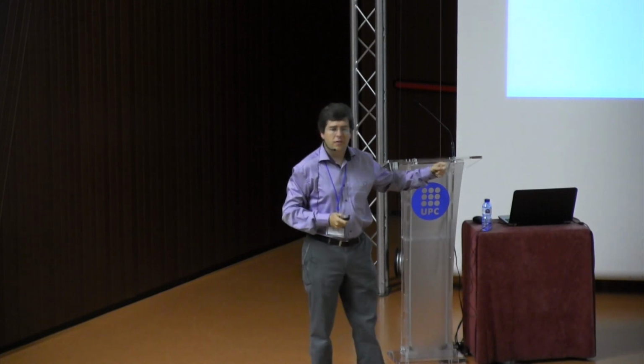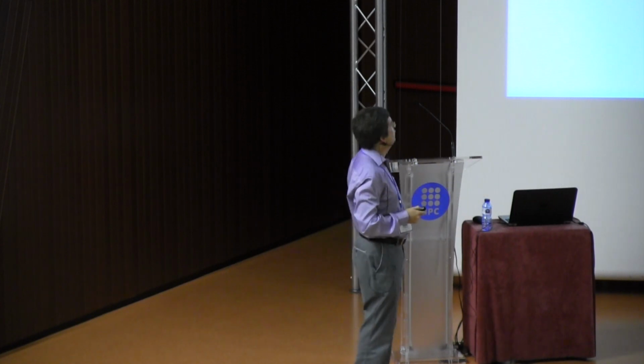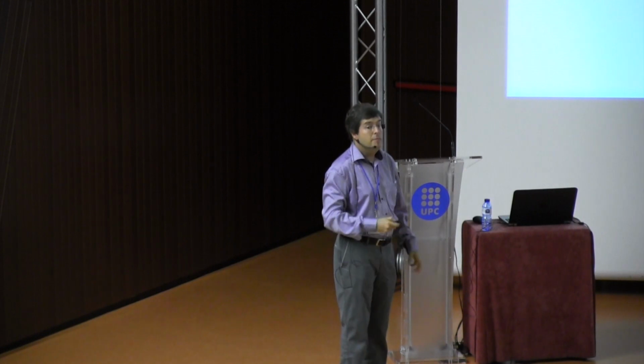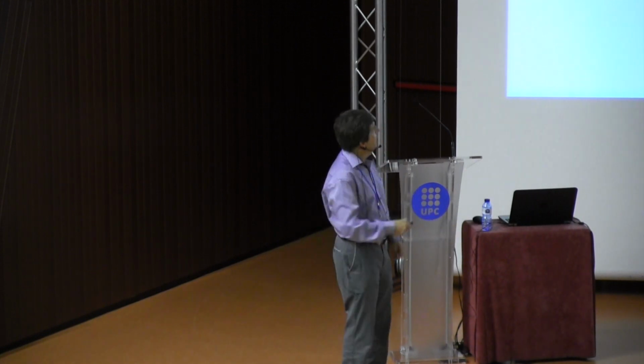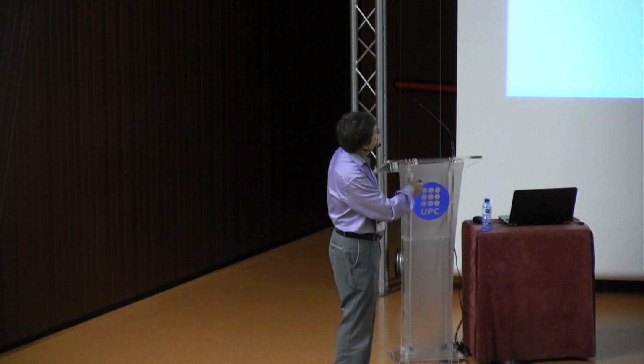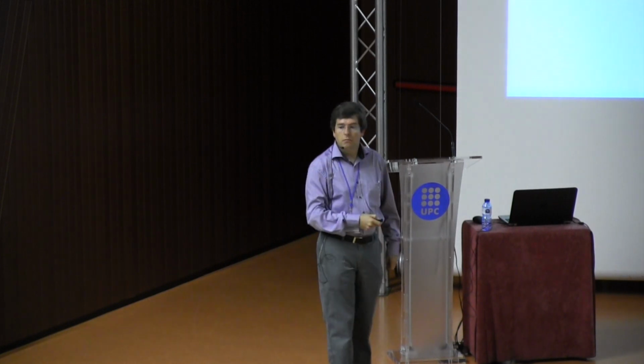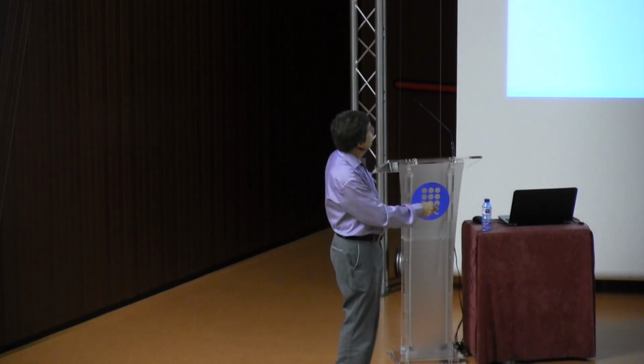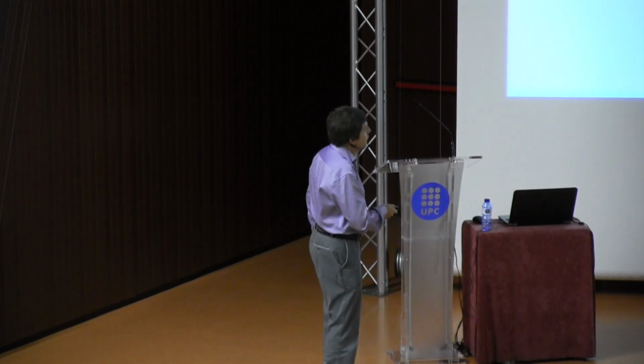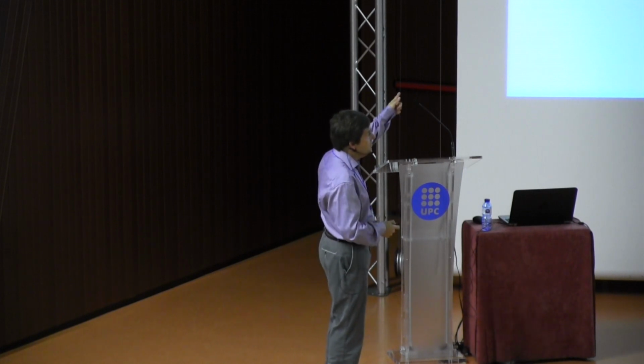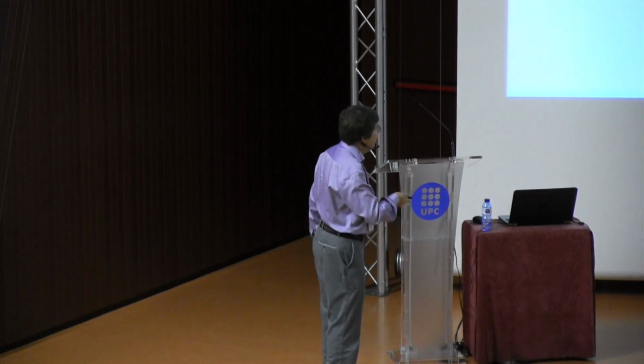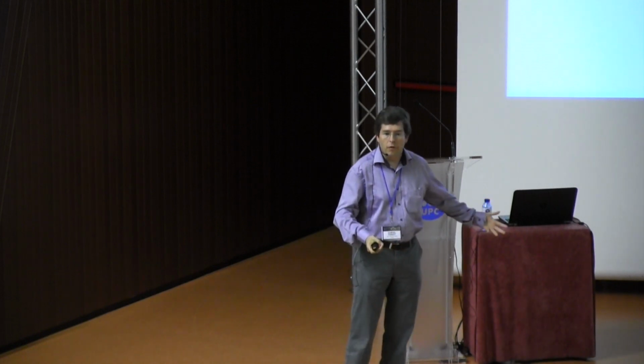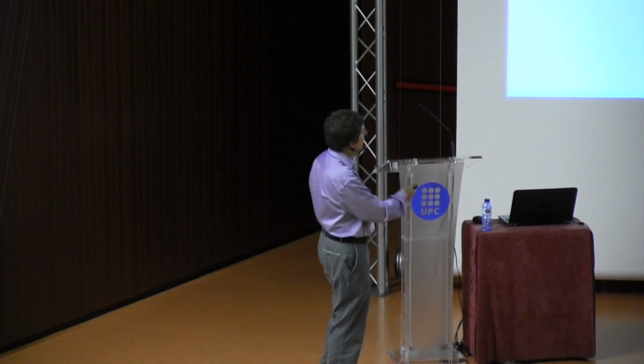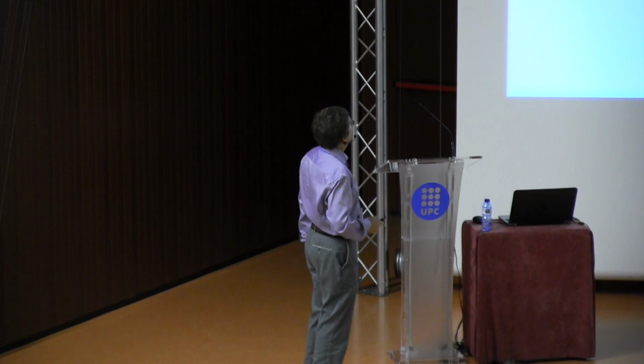If you use this damage model, this anisotropic damage model, in your finite element simulation, what you will get is mesh dependence, of course, as usual. If the mesh is coarse, the crack will propagate straight. If the mesh is fine, the crack will branch. Who is right? In fact, we know that the branching is observed, we have seen it in the experiment. But that's why we need the micro damage model for that, to regularize these simulations.